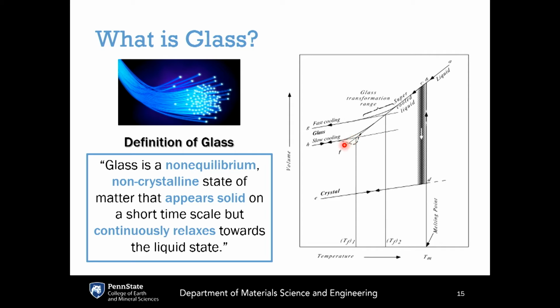And so when you consider this definition of glass once again, it's a non-equilibrium material. What does that mean? It's not the thermodynamic equilibrium. It also means that the state of the glass depends not just on its chemistry and its temperature and pressure, but its entire thermal history and temperature history. Here you see if you cooled the supercooled liquid fast, it freezes in the glass at a higher temperature because you've given it less time. And therefore, the structure of this fast-cooled glass corresponds to the structure of the supercooled liquid at a higher temperature.